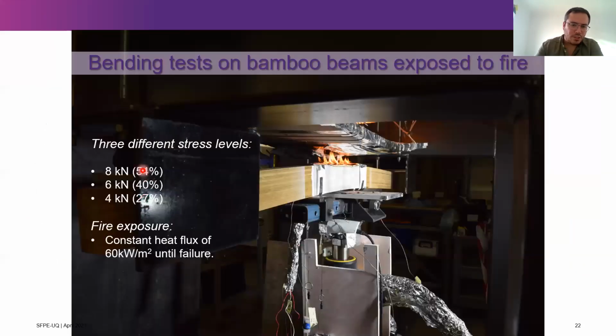With that information, then we define 3 different stress levels. We apply 54% of the failure load, 40% of the failure load, and 27% of the failure load. So remember that from the previous test, we defined our failure load, which was around 15 kilonewton.